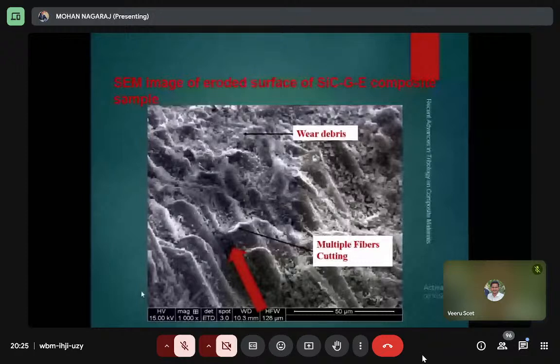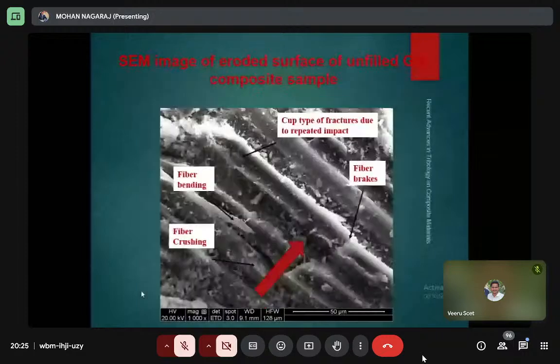SEM images of the eroded composites are observed. This is the unfilled composite, without any filler. More wear scratches, more fiber bending, fiber crushing, cuts and fractures are observed. Again, in the silicon carbide mixture, more fragmented fibers are observed. Here also crushed and fragmented fibers are seen in the SEM image of the surface.